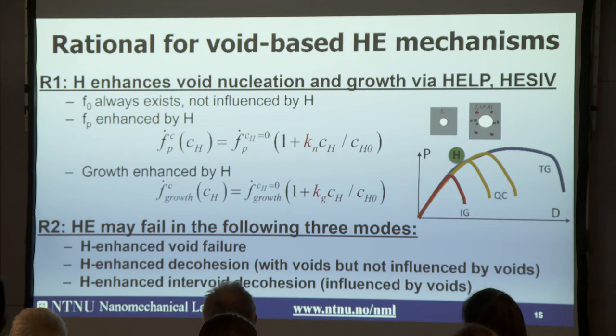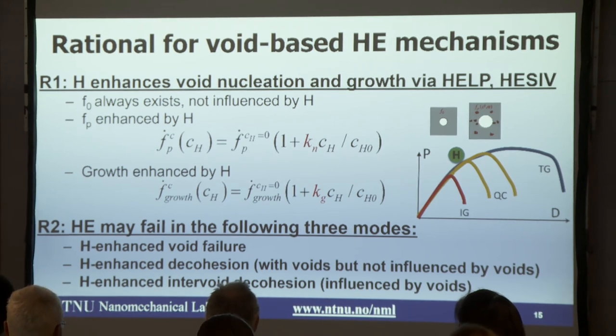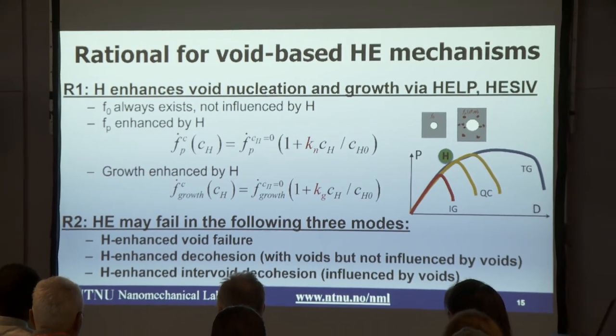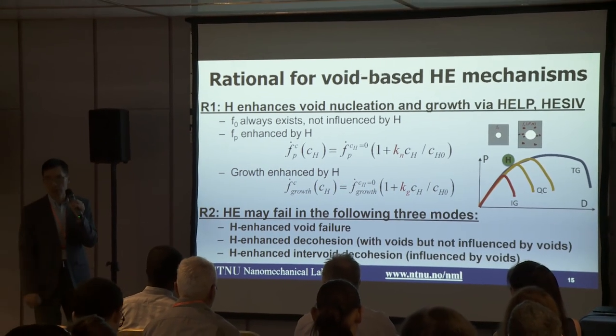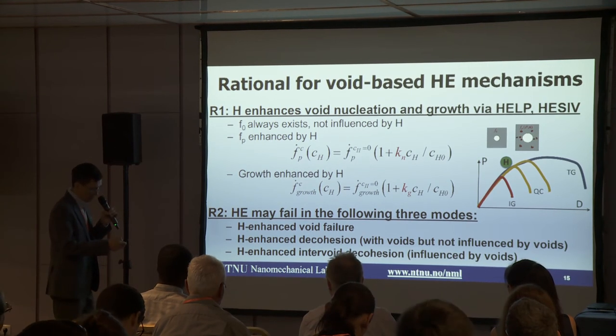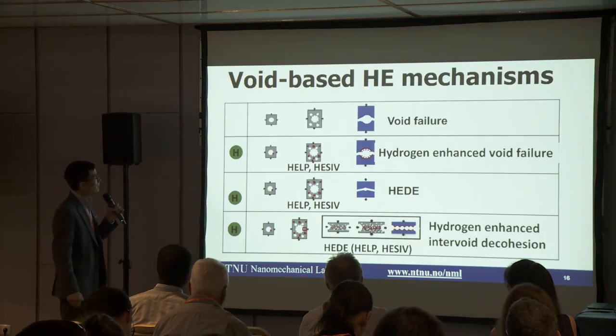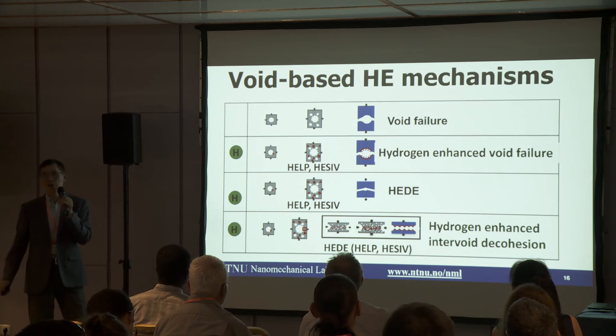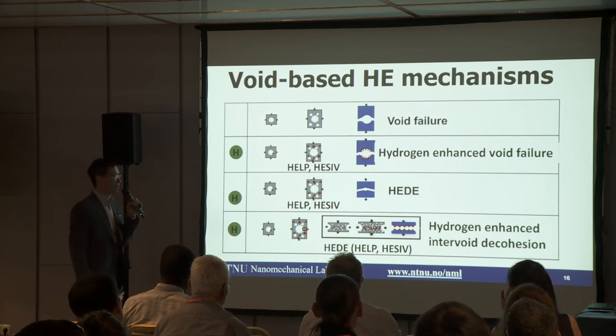Point number two: hydrogen embrittlement may fail in the following three modes. First, we can still have a void failure, but hydrogen will enhance the void failure. This is important. Second, which is difficult to understand, we have hydrogen enhanced decohesion, this is HEDE, but with void. However, the void does not have any influence on the HEDE, so HEDE is dominating. Then we have a third one, hydrogen enhanced intervoid decohesion. This decohesion will be influenced by void. So these are three outcomes of hydrogen embrittlement. Okay, so based on the rationale, I propose the mechanisms for hydrogen embrittlement as follows.